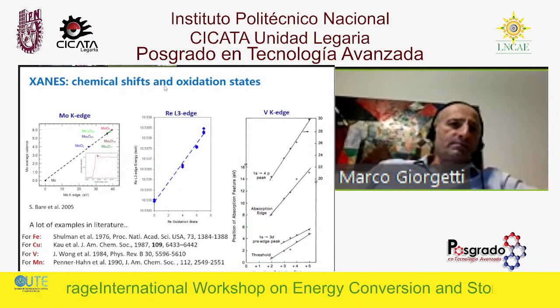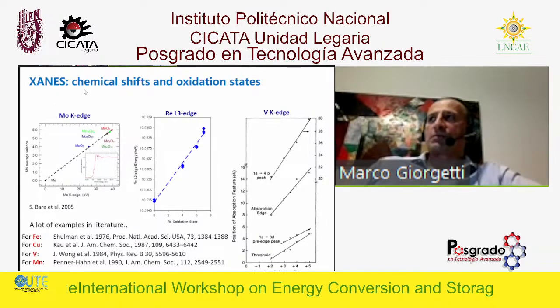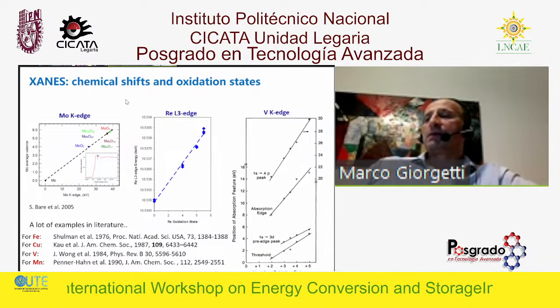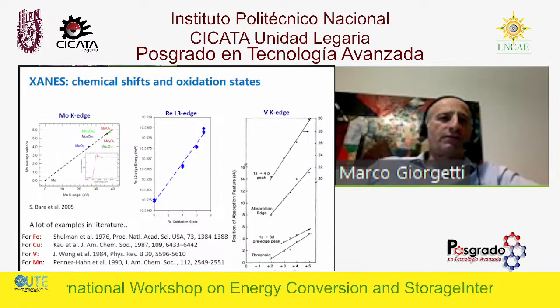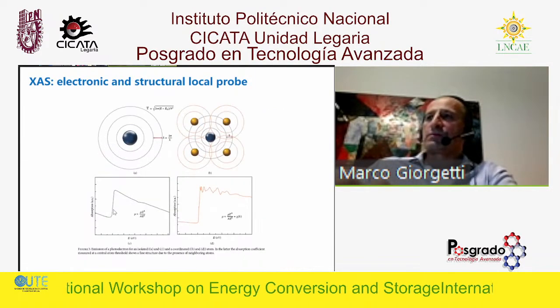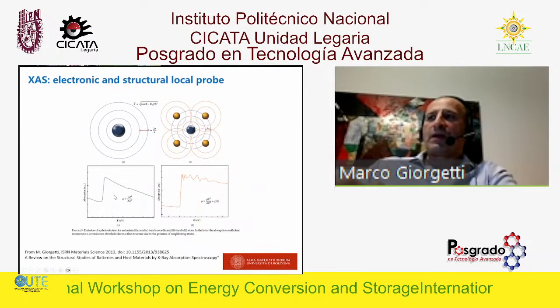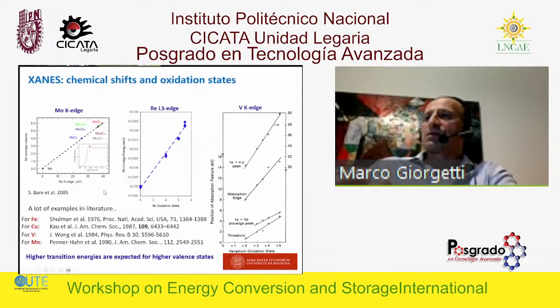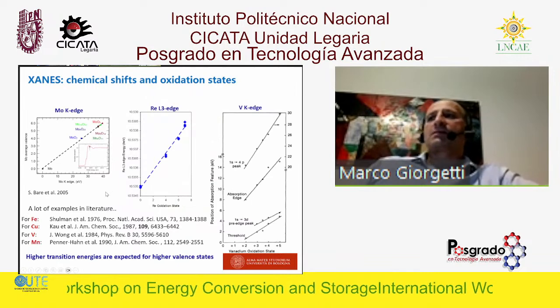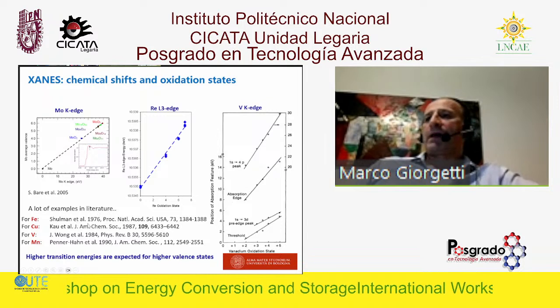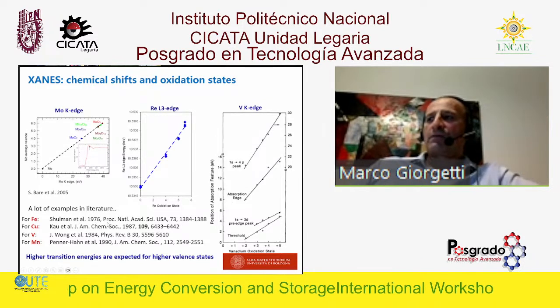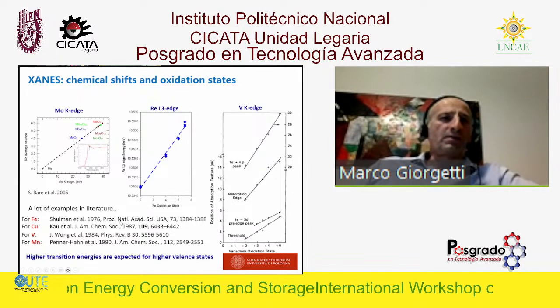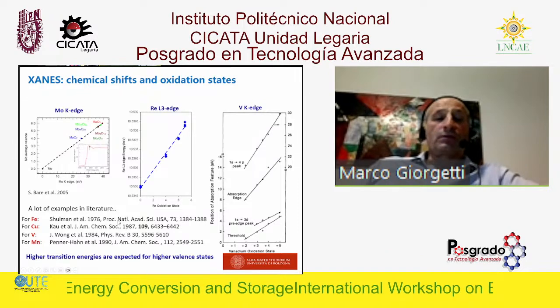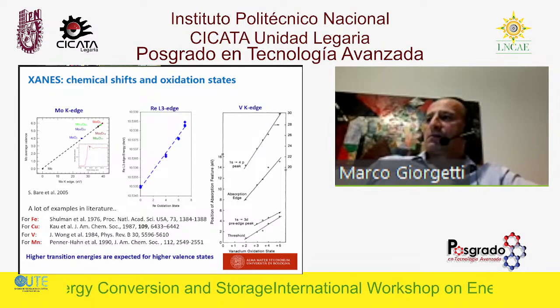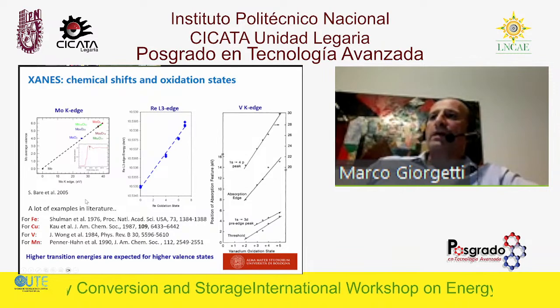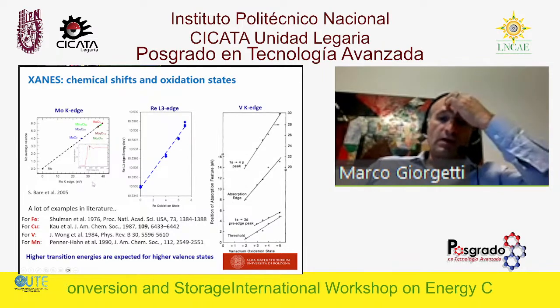And XANES. Okay, so we said that you have electronic information. Which kind of electronic information can you normally get? The easiest thing is to measure shifts. If you start from this and you measure oxidation, this goes completely to the right side. For reduction, this goes to the other side. We can just mention that there is a lot of literature about that. Basically, a high energy transition is expected with a high valence state. So this is something that you can use in operando experiments, but not only; if you don't have a clue about the oxidation states of some minerals or powders that you prepared, this is also a good way to measure the oxidation states of your sample.